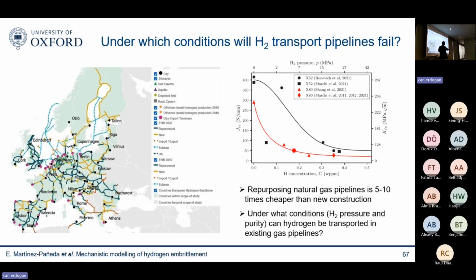So here you see the hydrogen fracture toughness. You see here fracture toughness. So pipeline steels X52, X80, they have toughnesses that are above 200 megapascals per meter. But the moment you bring hydrogen into the picture, you see 0.5 ppm, very small amounts, you're talking about 40 megapascals, 50 megapascals per meter. So not as brittle as a ceramic, but quite brittle. These are again experiments here that correspond to that hydrogen situation.